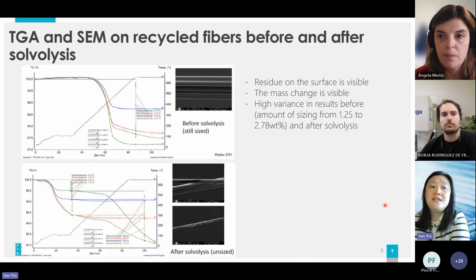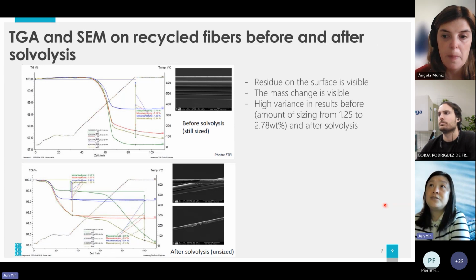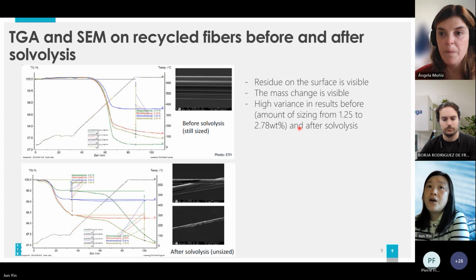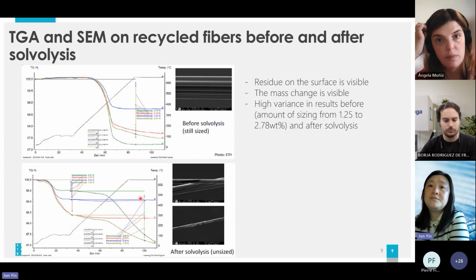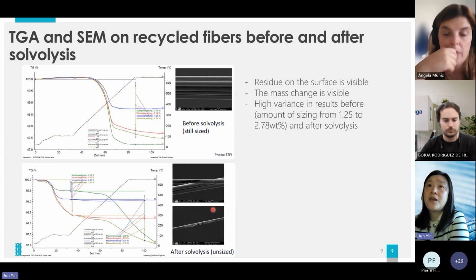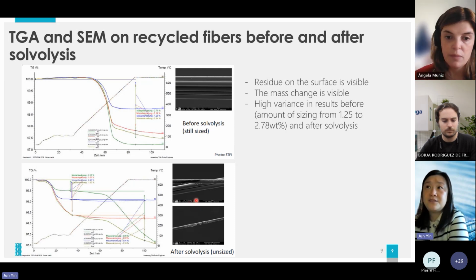Then by using TGA, we measure the recycled fiber before and after solvolysis. On the top is before solvolysis, and on the bottom is after solvolysis. We can see the residue on the surface is visible, and the mass change is visible. There's a very high variance in the result before and after solvolysis.